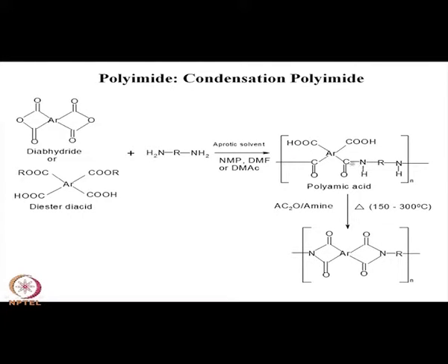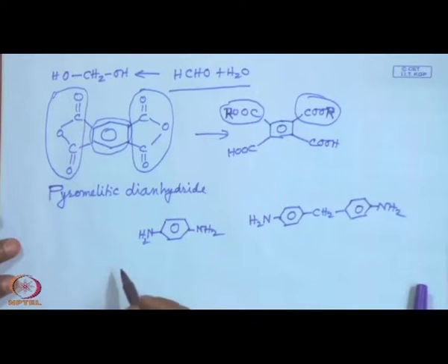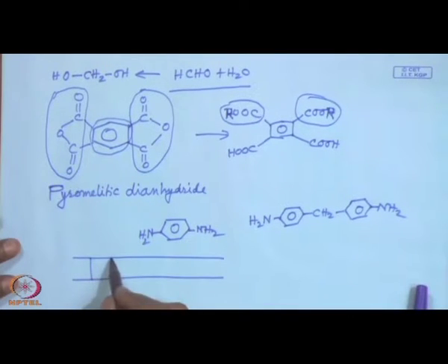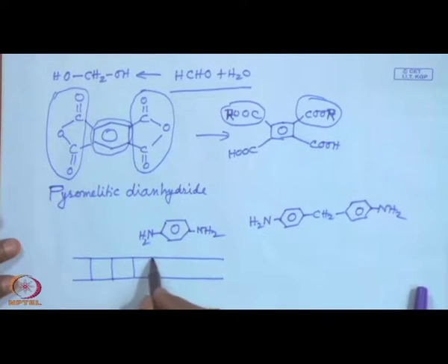Here you see this amide linkage is converted to an imide link by reacting with this carboxyl group, forming this imide ring. So, basically it forms a double strand polymer, or multi strand polymer, or ladder polymer, which looks like this, a ladder-like structure.